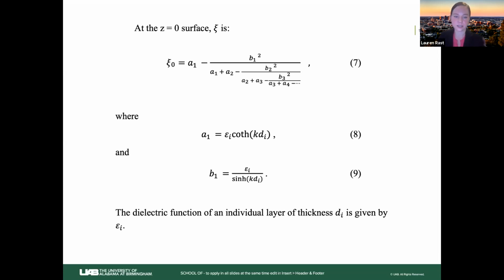Okay, so the dielectric function of an individual layer thickness is what's shown there. So the thickness d_i, and then this is given by, if I find the next expression here. Let's see. Yes, we have the composite function there. I'm going to show how we connect this in just a minute to the overall electron energy loss spectra, but I want to show first how we construct, if you look at this, we have A1 and B1. Those are expressions for individual layers. So we're inputting the dielectric function for an individual layer and the thickness for that layer into an expression. And so we need material properties for the components of these heterostructures. So where do we get the material properties? You can do this in a variety of ways, a really flexible way of calculating the overall effective dielectric function.